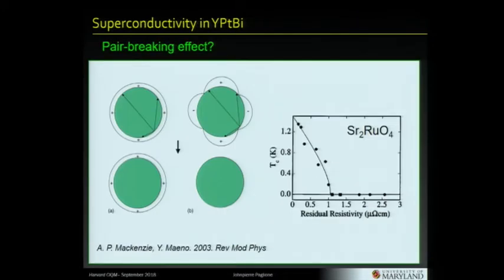One other piece of evidence that we have from more recent work is looking at pair-breaking effects, trying to help us understand the pairing state as well. Strontium ruthenate is a classic, I'll say quote-unquote, p-wave superconductor, because it's not concluded on, but it's certainly an unconventional superconductor. It's known really well in this system that it's very sensitive to disorder. All you need is 1 microohm-centimeter samples, and you can't even see the Tc anymore. This is a classic pair-breaking effect, Abrikosov-Gorkov pair breaking. That only happens in a system where you have some sign change in the order parameter, such that if you start putting in dirt and you cause scattering between plus and minus, you actually destroy the state.